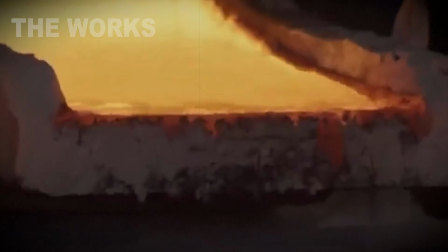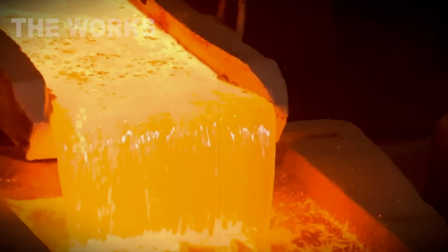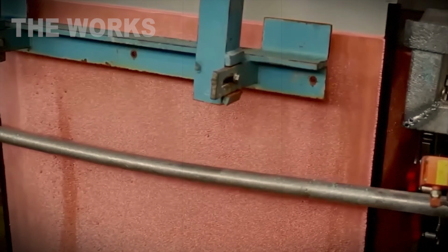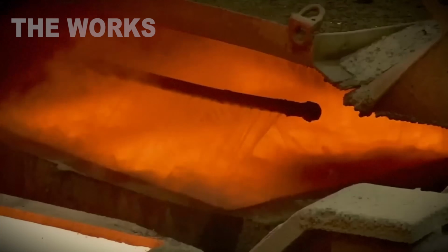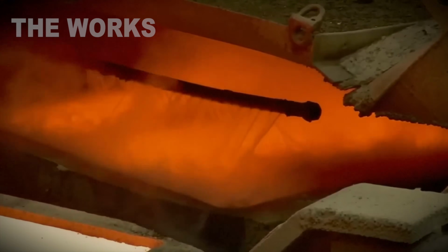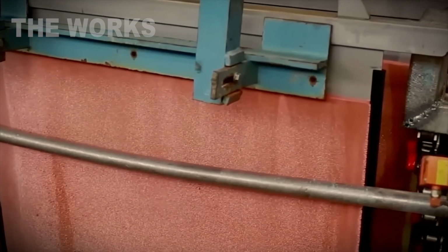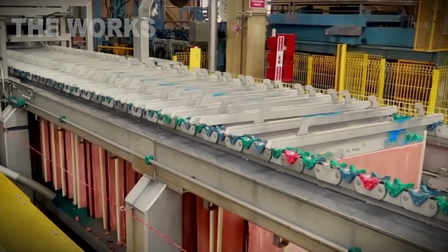At the bottom of the settling chamber, 2 melts separate. Matte, a molten copper sulfide at 65% copper content, and slag, a silicate melt with waste rock. The slag gets drained and processed separately. They still extract copper from it using additional flotation. The matte goes to the converter.